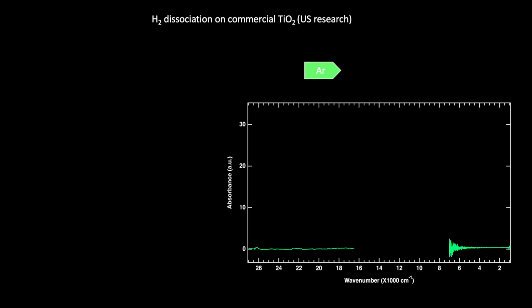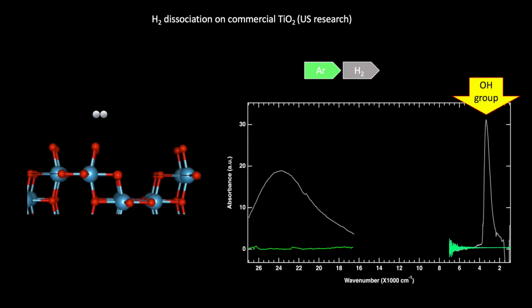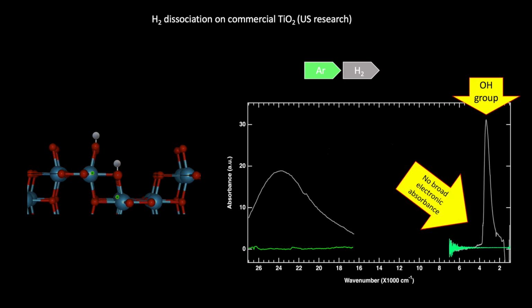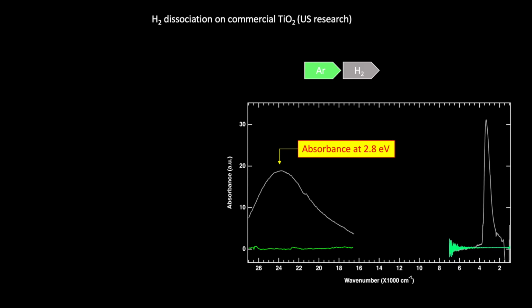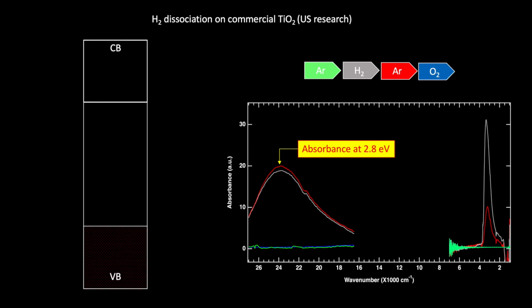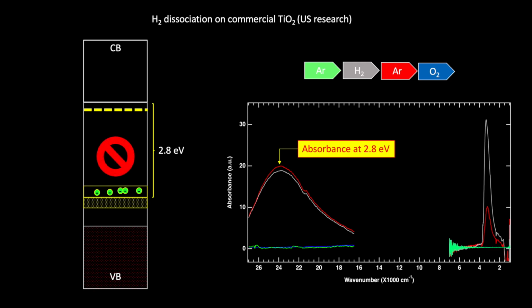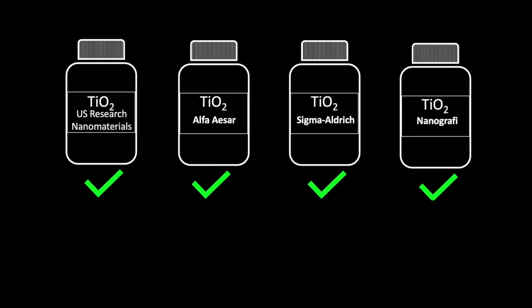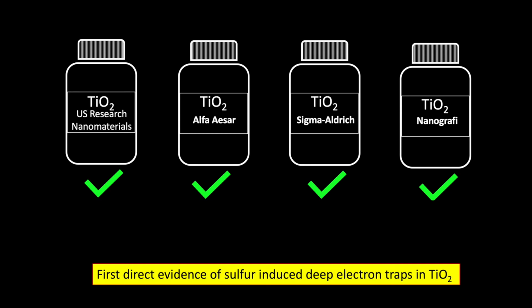In sulfur-containing samples, we did not see the electronic feature in the IR region, but we observed a strong absorbance centered at about 24,000 wave number under hydrogen. This feature was stable under argon and it quickly disappeared by reoxidizing the surface. These observations, for the first time, show that there are electronic states acting as deep electron traps 2.8 eV below the conduction band minimum. Electrons in these states are out of reach of IR photons, but photons in UV visible region could excite them into the conduction band. Comparing the results of 4 different commercial anatase samples with pure material provides the first direct evidence for the presence of sulfur-induced deep electron traps in titanium dioxide.